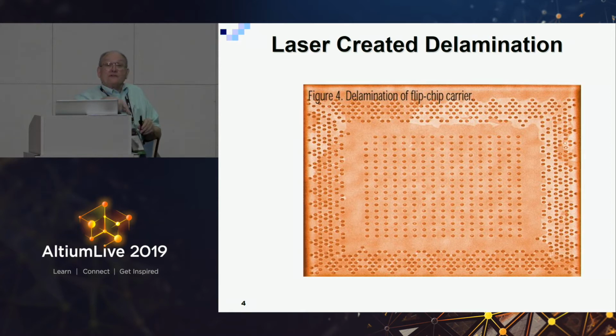But nobody bothered to tell you that you could be buying bad boards, because not all boards are good and not all fabricators are equally capable. But you ask, do they use an ultraviolet laser or an infrared laser? If they're using an infrared laser, then you need to see the specs of the pulse width, the energy level, and the frequency of that laser with respect to the material that you're specifying, and whether they've done some test runs to find the energy dispersal for that material. It's very, very complicated. It's not the same as RPMs and a twisted drill, which is quite simple compared to the involvement of lasers.